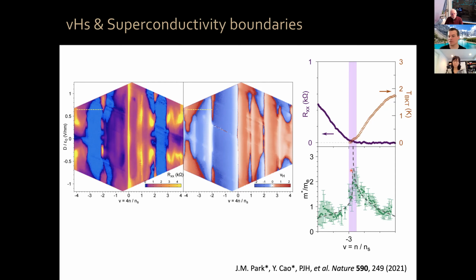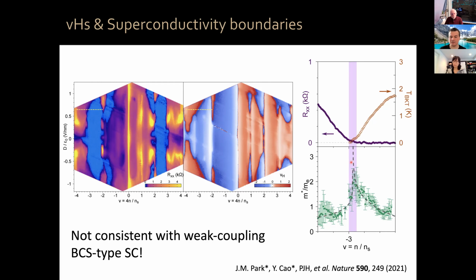singularity. Okay, this is very much unlike typical weak coupling BCS type superconductivity. Okay, in a typical conventional superconductor, as your density of states increases, your TC grows exponentially. Here, as our density of states increases, TC not only doesn't grow, it actually decreases, and it becomes 0 at the point where you have the maximum in the density of states. Okay, so this is very unlike weak coupling BCS type superconductivity.